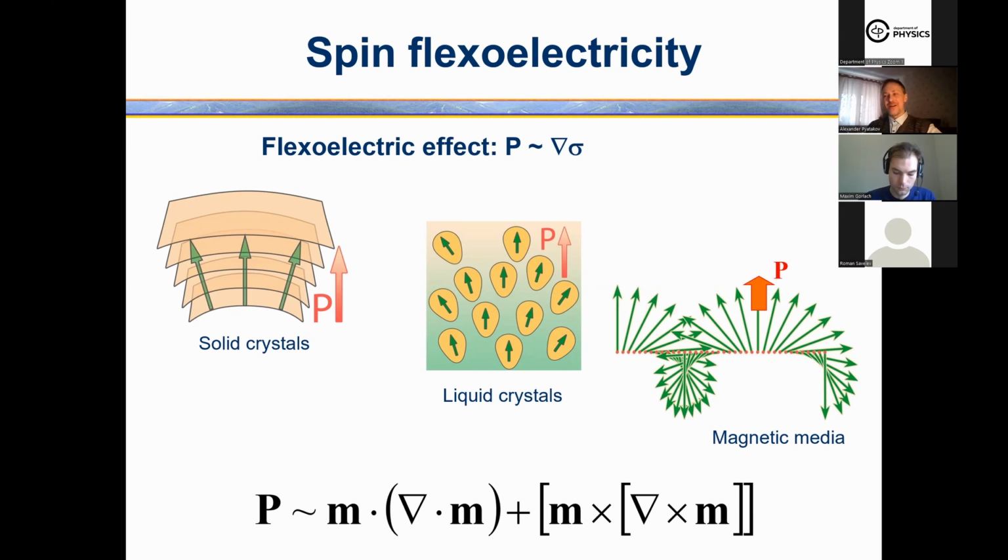Why is it so? Because it's more interesting: when there is a linear term, that means that the polarization depends on the direction of rotation, clockwise or counterclockwise. So you can adjust even the direction of polarization. You can switch electric polarization by switching the cycloid from clockwise to counterclockwise.